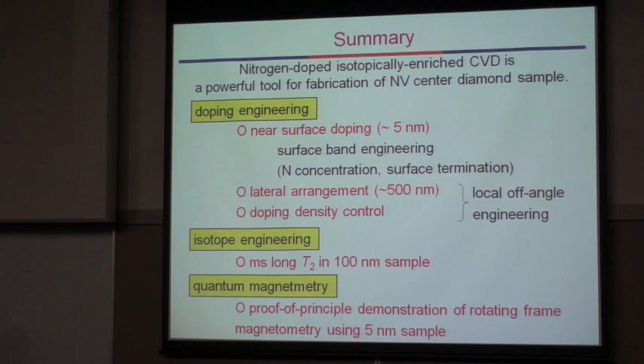So here is a summary of my talk. So we demonstrated the doping control in nitrogen-doped isotopically enriched CVD method. So as a result, we can demonstrate near surface doping by engineering the surface band structure. This surface band engineering can be done by changing nitrogen gas concentration and by changing surface termination.